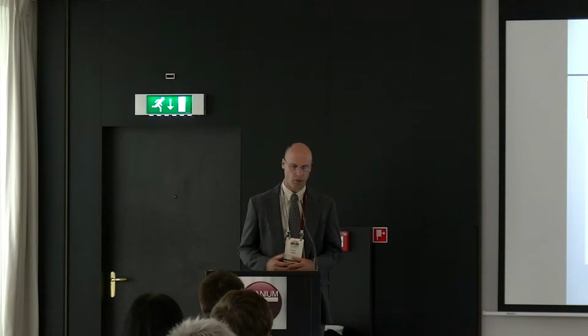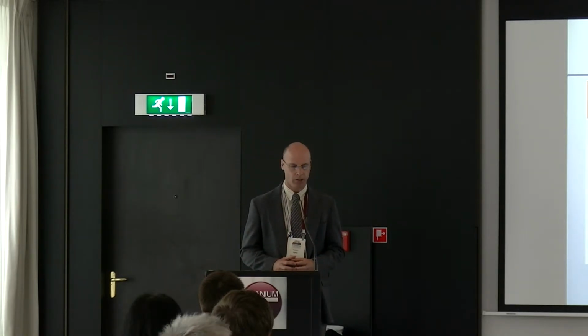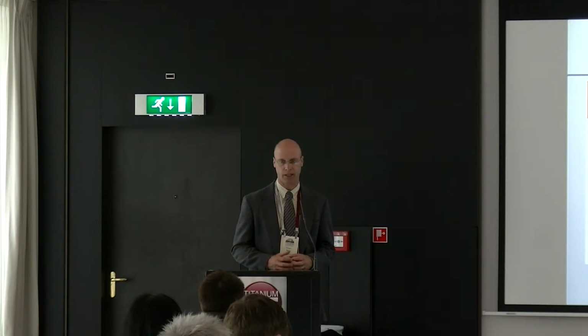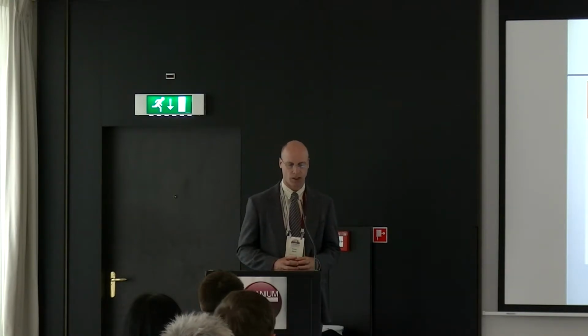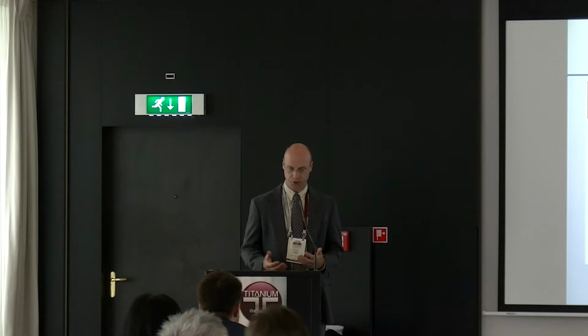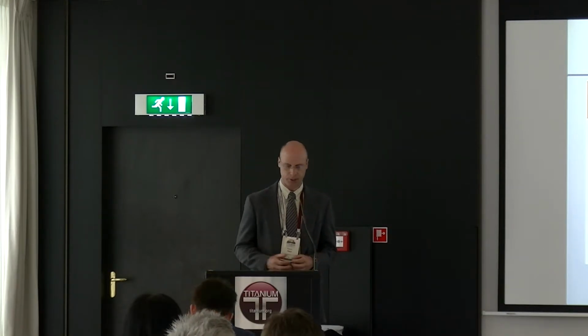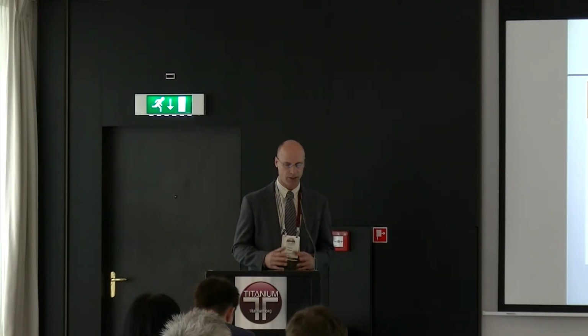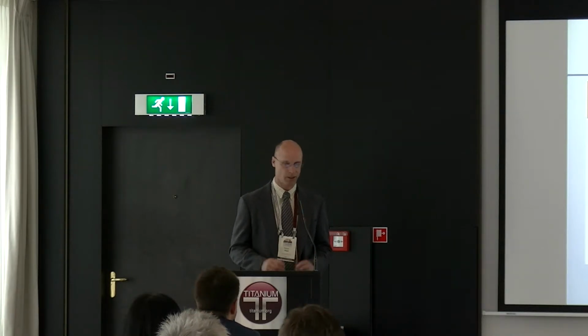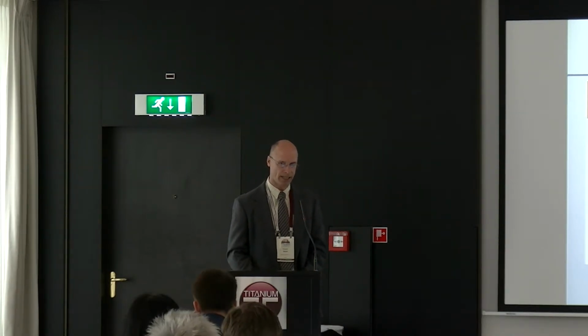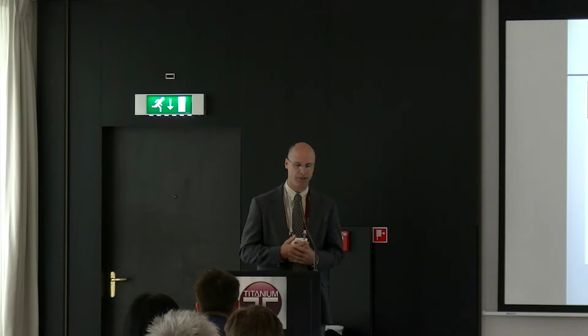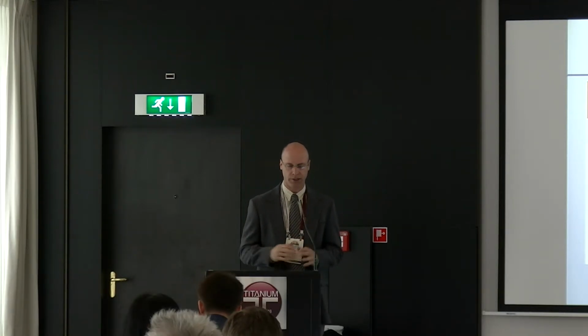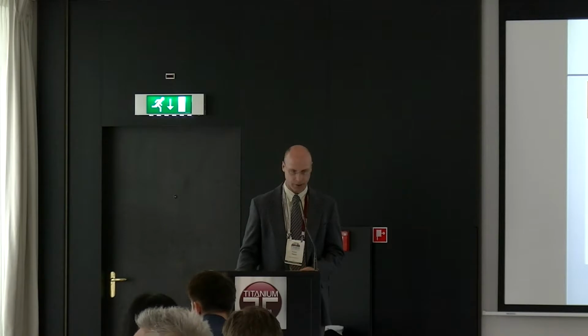So overall, we combined all these factors evenly and gave them an even weighting. So vacuum arc remelting, we would give a fair rating. Electron beam melting for the titanium aluminides, probably not the technology of choice. Cold wall induction melting, very good. Plasma arc melting, anticipated to be very good. And the induction levitation melting, only because there are still some unknowns about the exact quantities of how much you could levitate at one time, we rated somewhere in the fair to poor category.